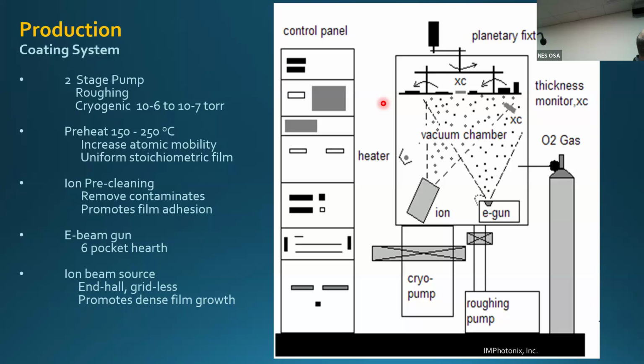Again, we use the E-beam, electron beam gun, for evaporating those materials I showed earlier. The reason is that you need something like around 2000 degrees C to evaporate many of them, and the only way you can get that much energy is with an electron beam gun to do physical vapor deposition. And again, the ion beam actually assists in the deposition. Also, we plasma clean the surface of the substrates with the ion beam to remove any contaminants or monolayers to get good adhesion.